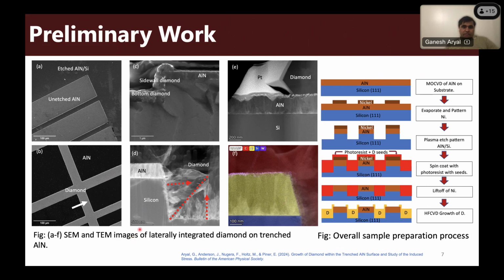If you see that, this is the aluminum nitride on the silicon, and the diamond was growing both vertically as well as horizontally in the trench part. And the interface looks very smooth, so we can anticipate that it acts as a good interface for charge carrier transport.